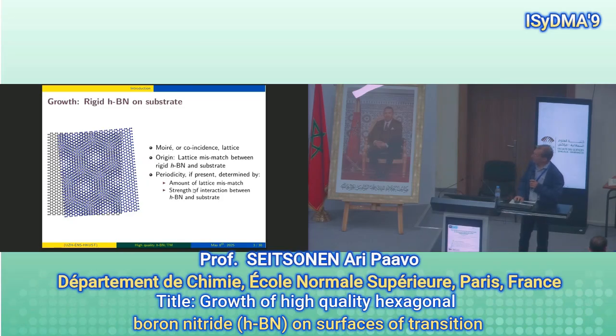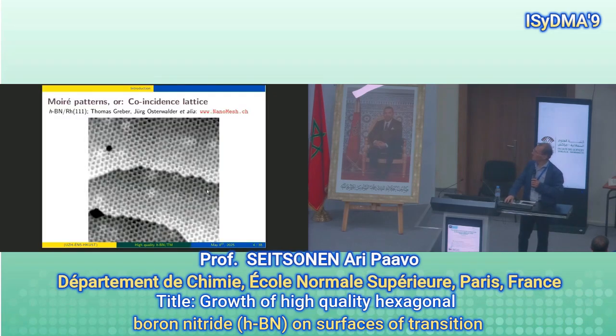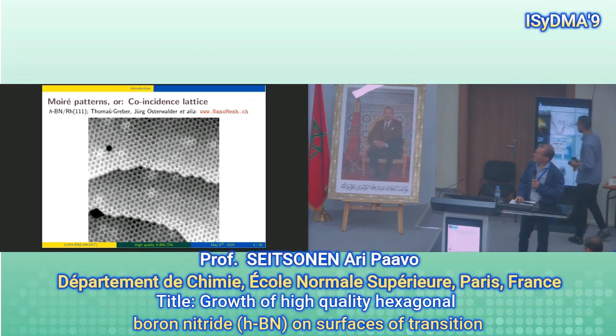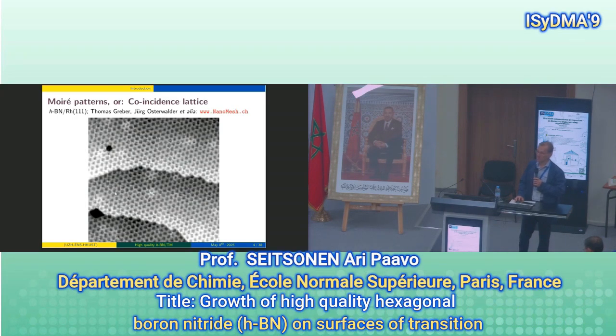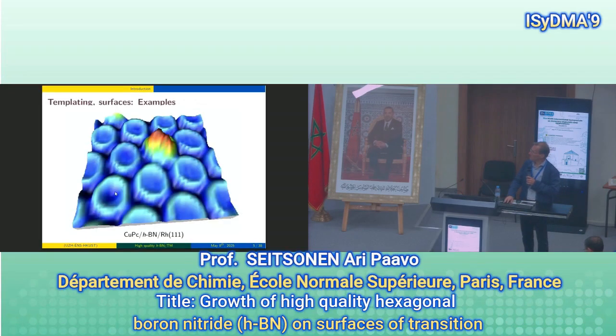And the size of the moire, well, it depends on the lattice mismatch. So how different are the nearest neighbor distances in the HBN and the substrate, and the strength of the interaction. So whether the HBN adsorbs strongly or weakly on the surface. And here's an early example. So this was the so-called nanomesh. It's Thomas Greber, Jürg Osterwalder, and their colleagues, entitled Nanomesh, and this is the STM image. So surface science techniques were used to characterize this structure.